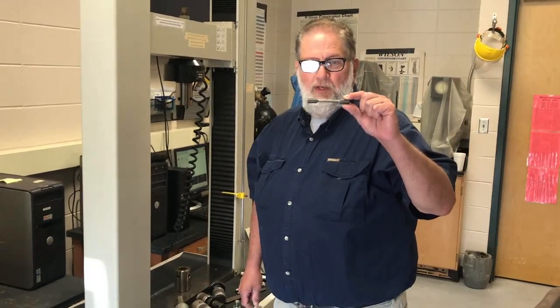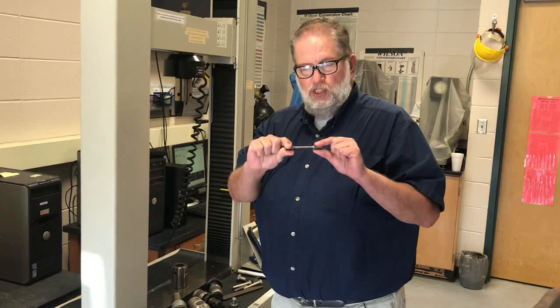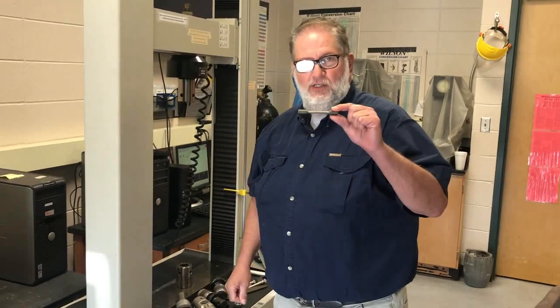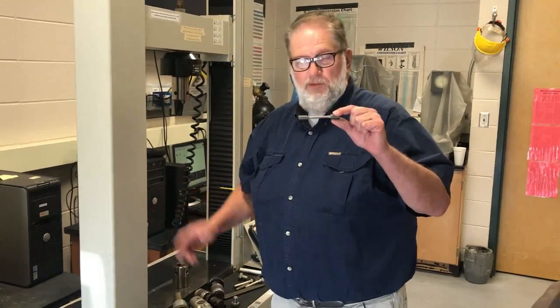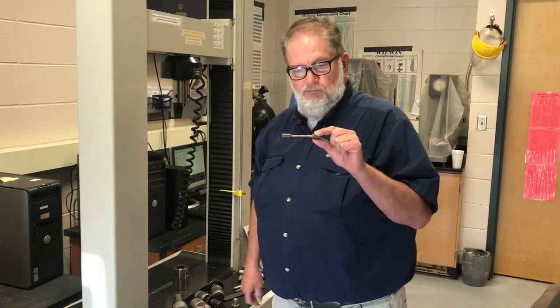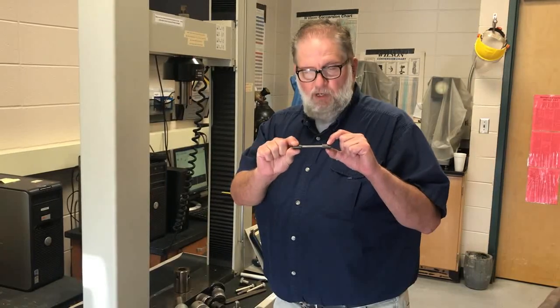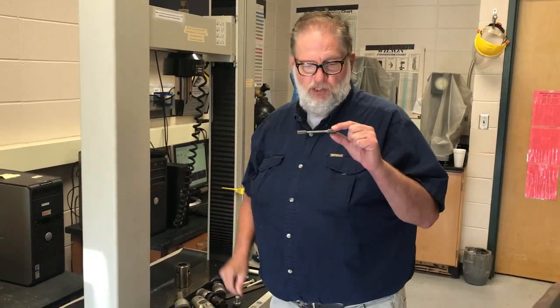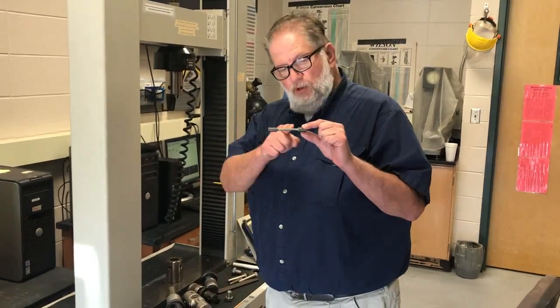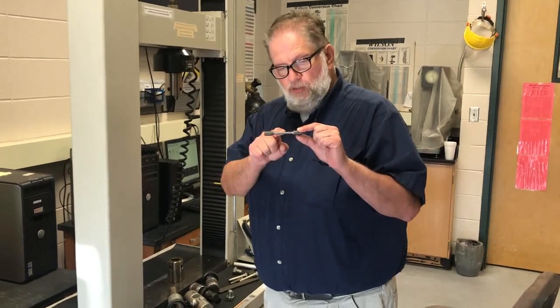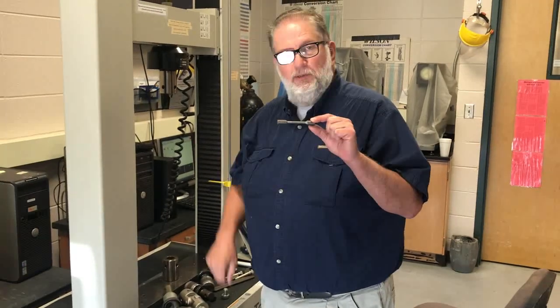Before we attach the sample to the tensile test stand, I thought I'd talk a little bit about the shape and size of a tensile test sample. You'll notice that the sample is threaded on each end, and that the center portion of the sample is of a smaller cross-sectional area than the rest of the sample. And that's for a very important reason. When you perform a tensile test, hopefully you know that we're stretching the sample, and we want to make sure that the area of highest stress, which would be in the area of smallest cross-sectional diameter, presumably, is in the middle of the sample. We do not want the sample to fail in the threaded region, because that would indicate a singularity stress concentration that we could not measure. So we use a sample that has the smallest cross-sectional area in the center, which focuses the stress in that area. And by the way, that cross-sectional area has to be pretty well known.